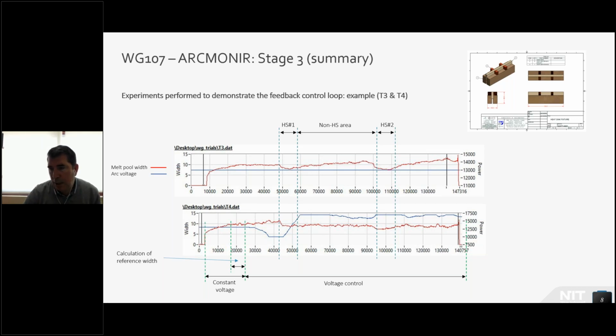This is the behavior that we have seen in stage 2, so it fulfills the experimental results of the previous phase. And then we can see in this area where there is no heatsink that the melt pool starts to grow again. It goes around 12 millimeters, and then when the process passes next to the second heatsink, the melt pool is again reduced, and then it goes up again. So this matches the experimental results that we have found in stage 2.